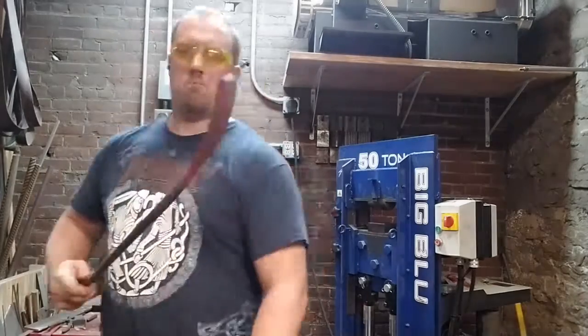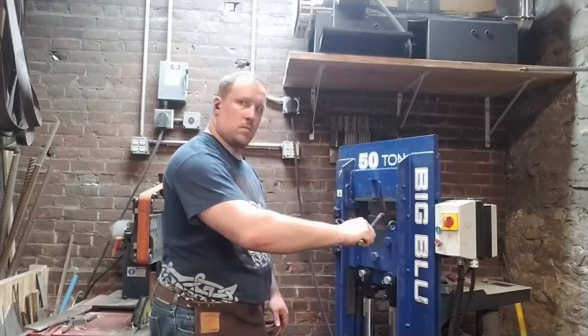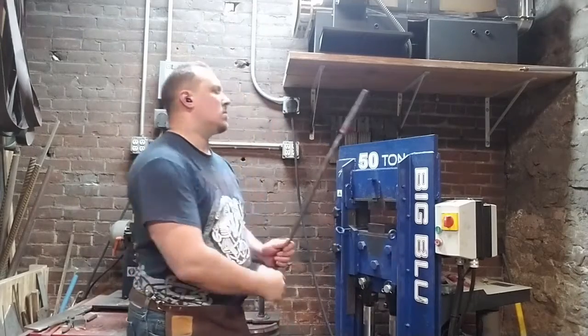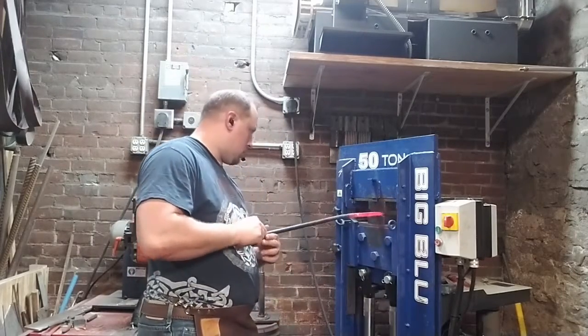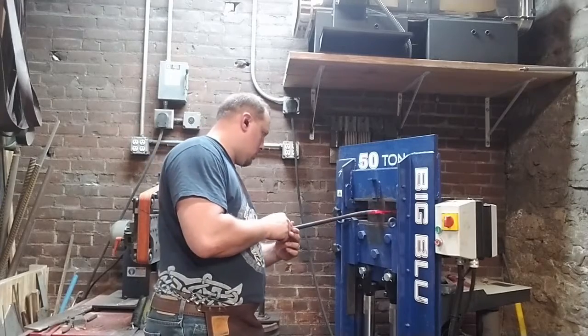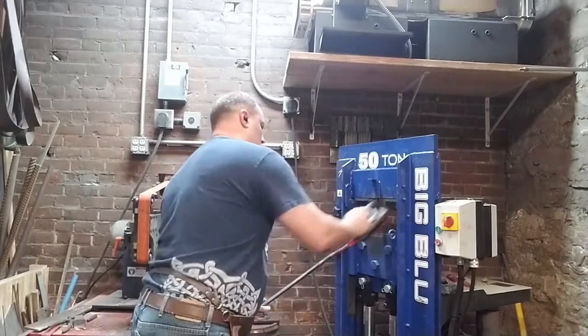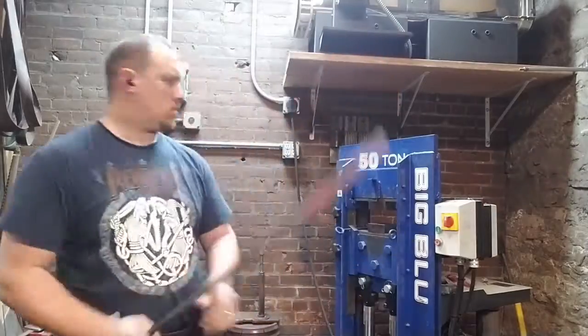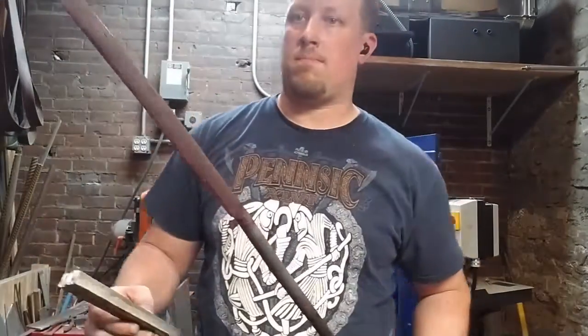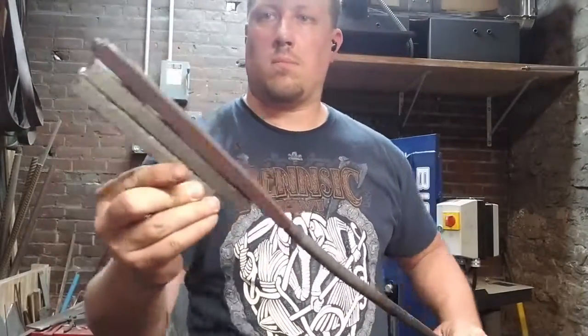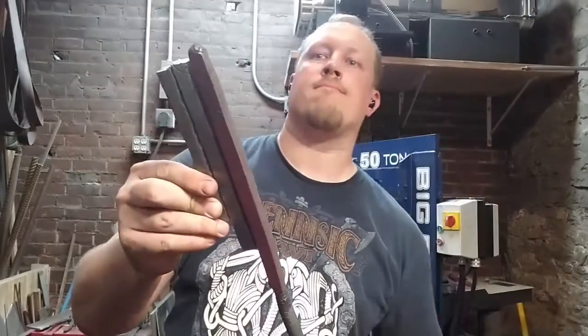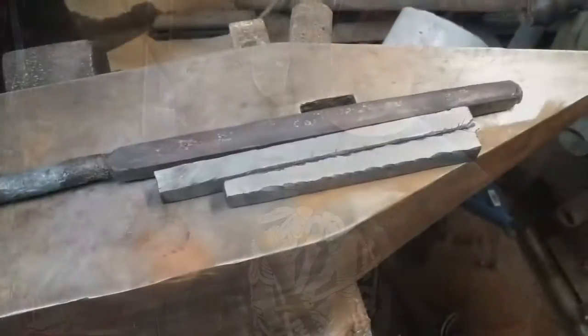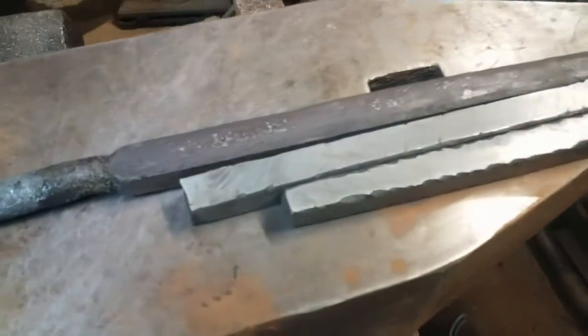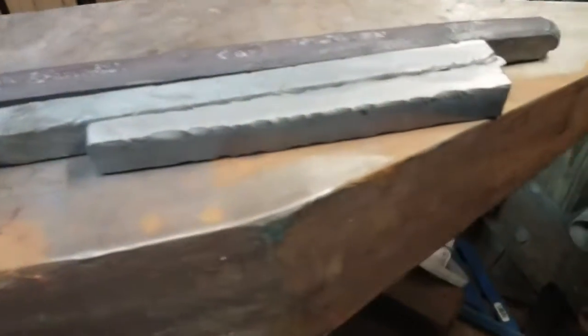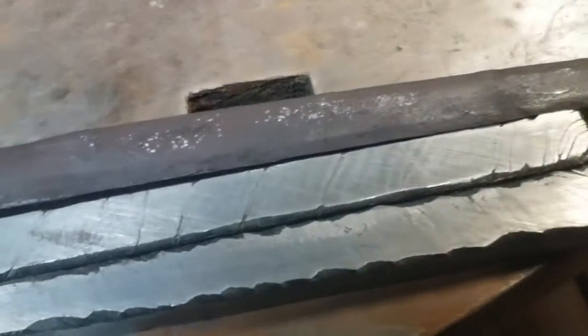Here I've got the fullering die on the billet, and I'm forging both ways. And I did see the seams on just the very edge start to open up, but no, it came out very nicely. We were able to get a very nice, clean billet, and here they are. Here are our 3 pieces of parent metal, and next we're going to try and forge a Seax.